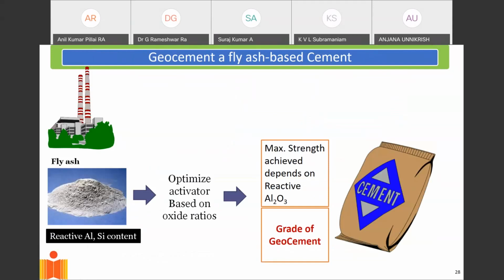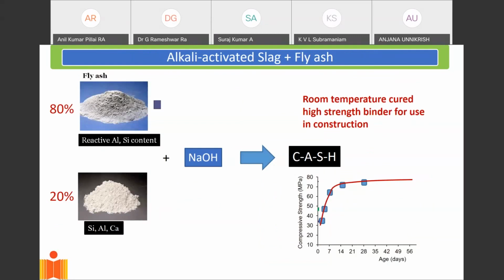This process has now been developed by us, where we take the fly ash, we optimize the binders, and we're able to package this material in the form of a cement, where you simply take it, mix it with water, and you can use it to make concrete, which is very, very strong.